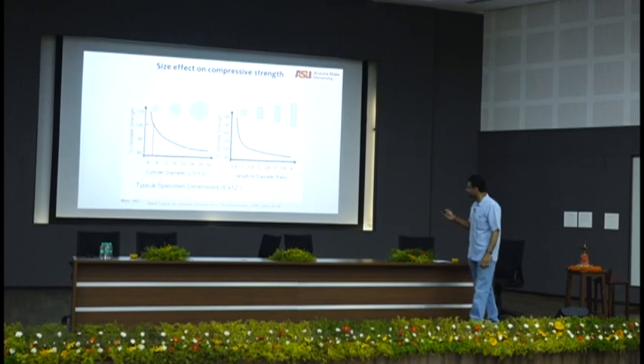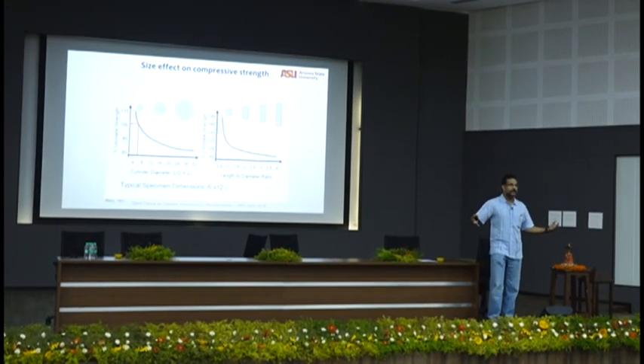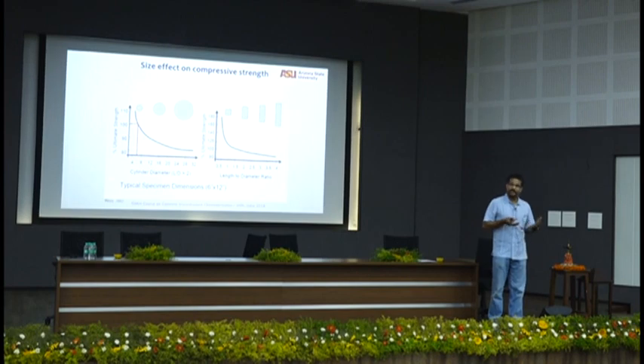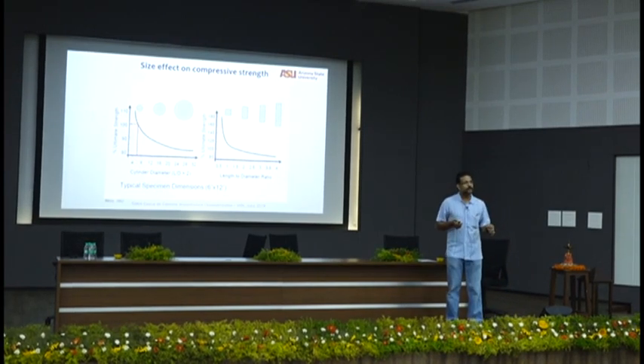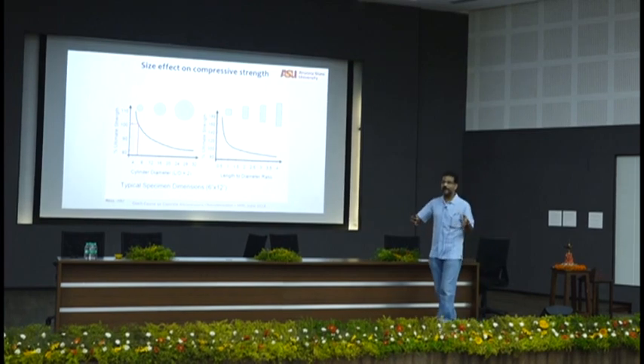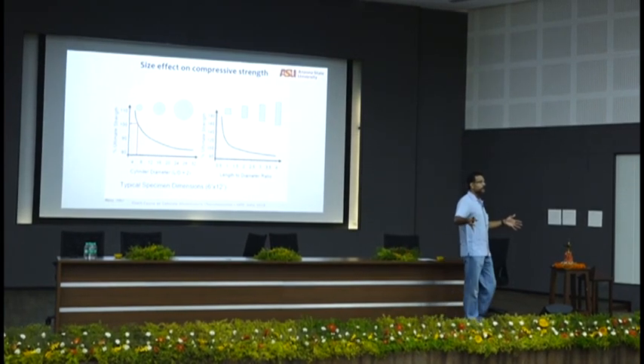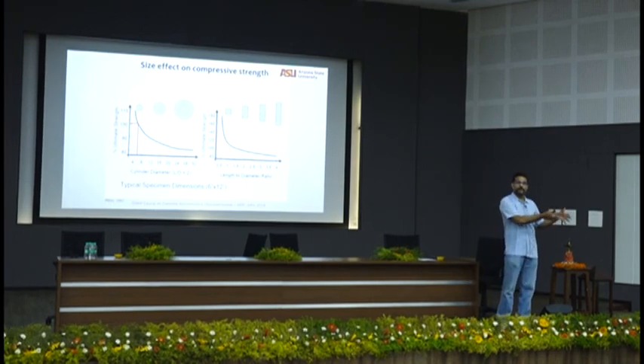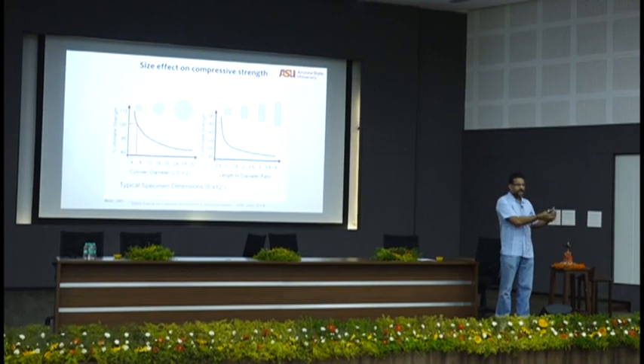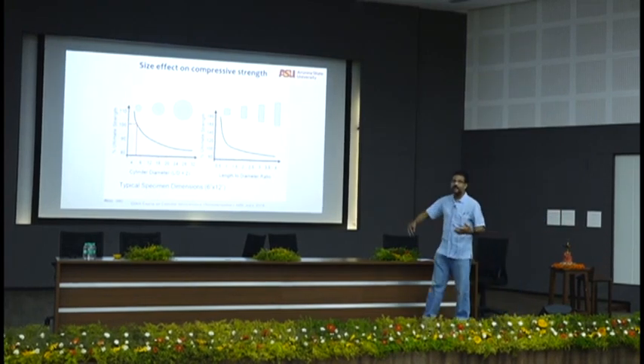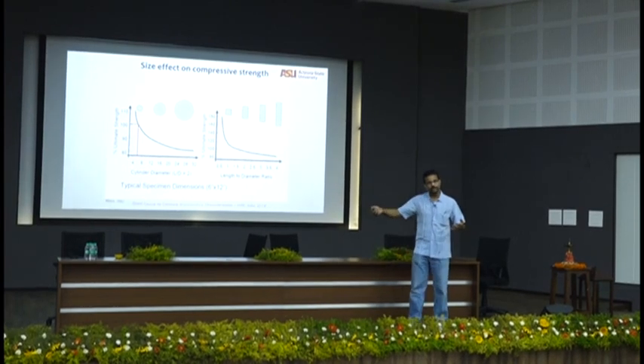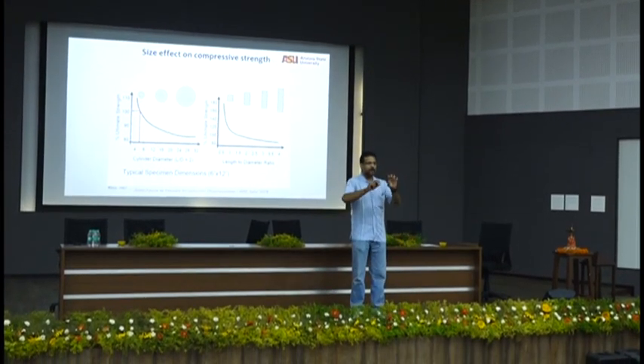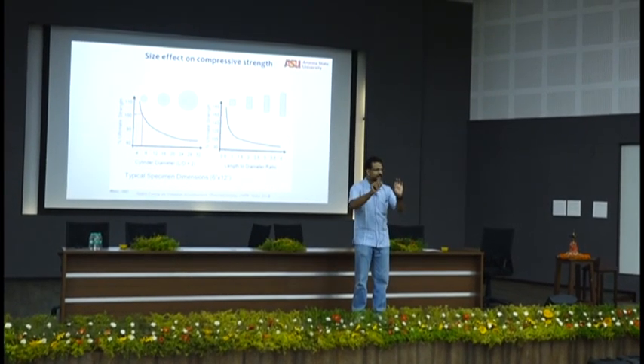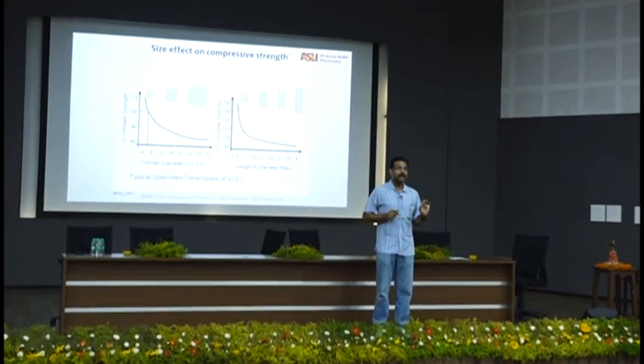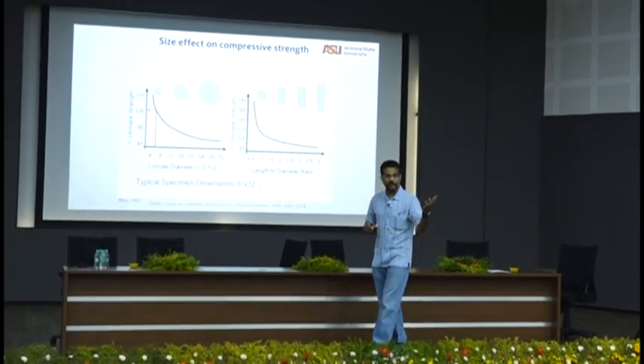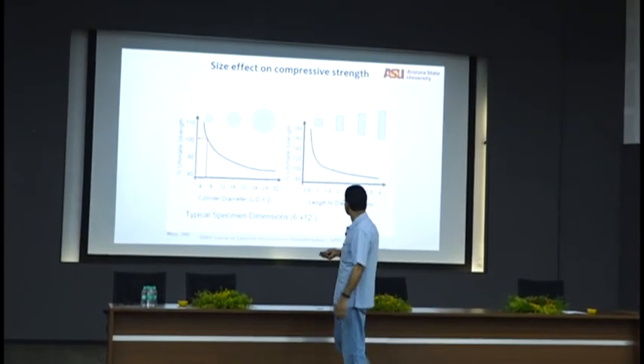Okay. Size effect on compressive strength, you will know that the larger you make your specimen, the weaker it gets. So your best option is to make a real tiny cube, right? What is the reason for that? Why do you have a 300 mm cube showing you a lower strength than a 150 mm cube, showing a lower strength than a 75 mm cube? Material defects. When you make larger and larger specimens, the chances that you have defects in that material is larger. If I can theoretically take atoms and connect all the atoms together properly, I should have no size effect at all. I should have the highest strength for that case, but that doesn't happen.